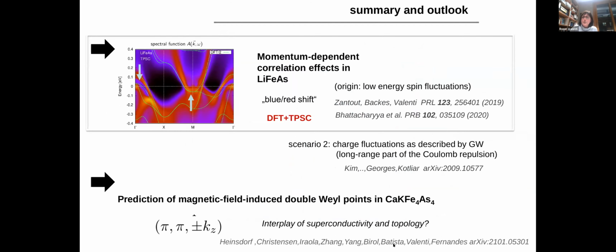So the second part was to show you that it is possible to have magnetic field induced double Weyl points in these 1144 materials by application of a magnetic field. And in fact, the Weyl points that we found are very near the Fermi surface. So for instance, by using doped materials, in order to bring down the Fermi level, one could have these Weyl points at the Fermi surface. And what may be very interesting is to investigate the interplay of superconductivity and topology. And the first part, what I showed you is the effect of non-local correlations in iron-based superconductors in order to understand some features of the spectral function in these materials. And with that, I would like to thank you for your attention.